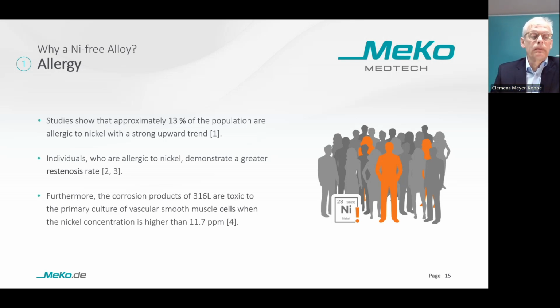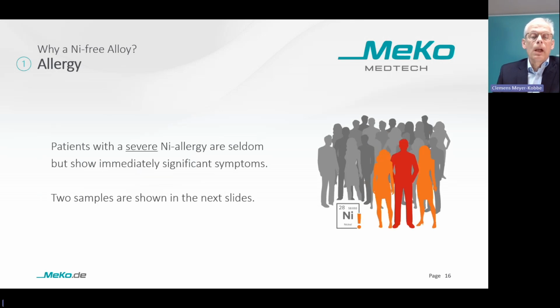There's also a study on the level of cells, which investigated the reaction of cells to nickel contents. The study proves that the corrosion products of stainless steel, the 316L, are toxic for primary cell cultures. Out of the group of patients with nickel allergy, so the group of about 13% with nickel allergy, a few patients show a severe allergy. In the picture shown as the man in red. These patients with a severe nickel allergy are seldom, but show immediately significant symptoms after a stent implantation. Two samples are shown in the next slides.